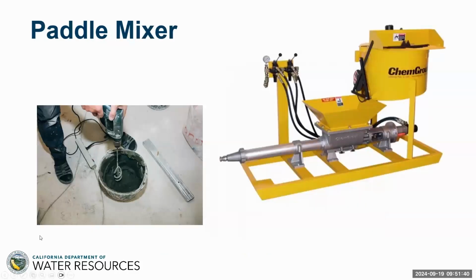And then the paddle mixer. Well, as you can see, there's paddle mixers and there's paddle mixers. The shot on the left-hand side, which I'm very grateful for and I'm going to use in other presentations, reminds us that typically handheld equipment like this would be regarded in our field only as acceptable for lab scale, bench scale testing. It wouldn't be acceptable in the field, partly because of the quality of the grout and also the volume of the grout and the time that it takes.